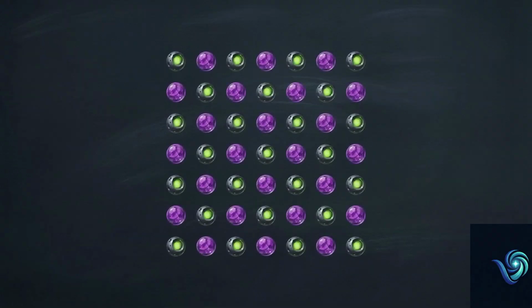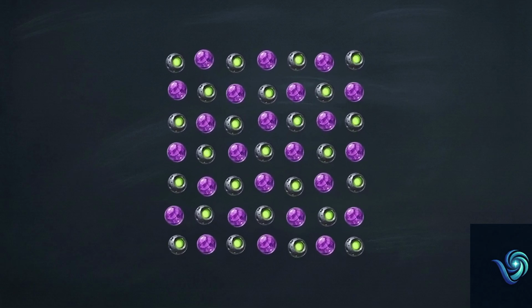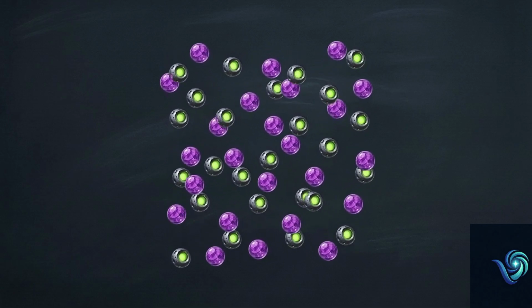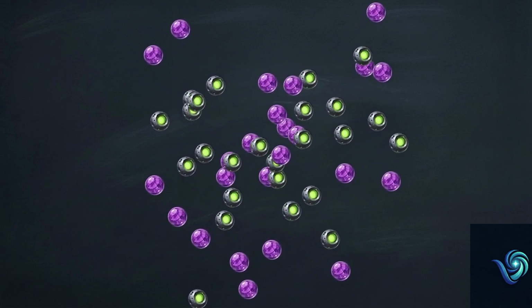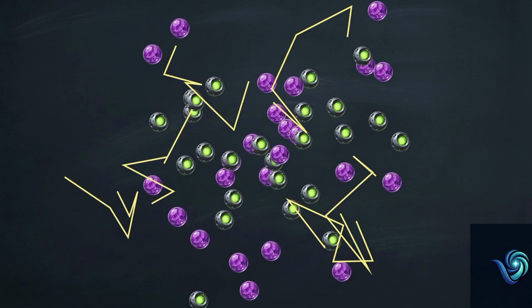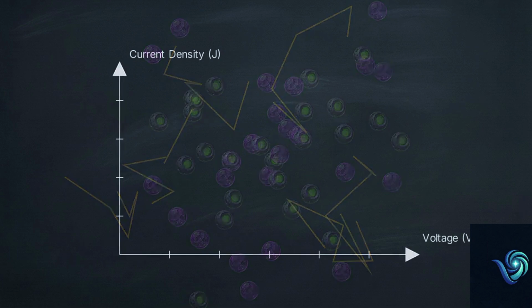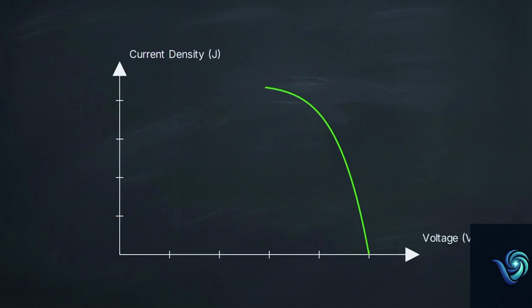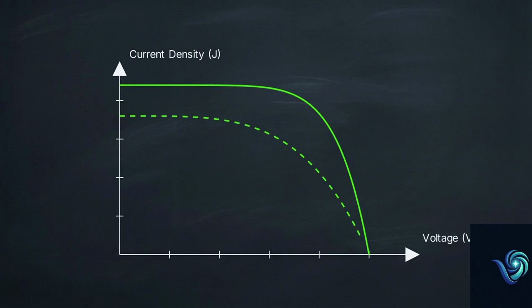The lattice is also soft. Under applied heat or electric bias, halide ions migrate through the structure. This creates internal electric fields that disrupt the cell's operation and kill efficiency. This internal ion movement produces a measurement ambiguity known as J-V curve hysteresis. This graph demonstrates the effect. Scanning from forward bias to short circuit produces a completely different curve than scanning from short circuit to forward bias. This wide hysteresis loop inflates reported laboratory efficiencies.